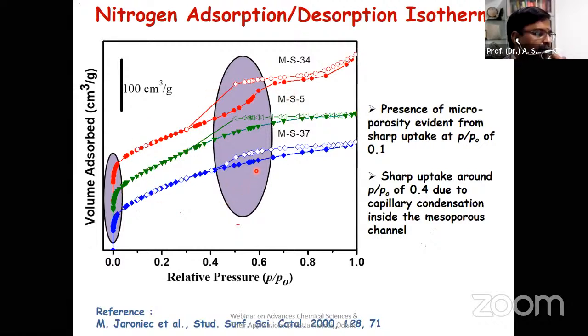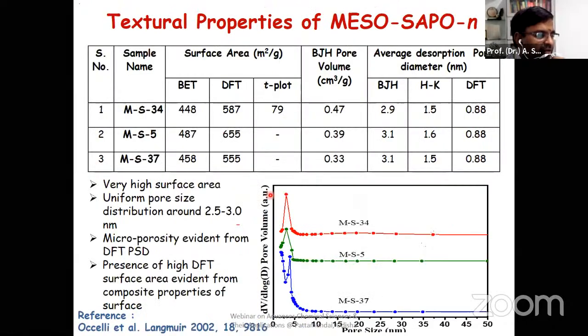How this is going to form, you can see from here. So the material formed has a meso-micro characteristic nature, which we normally confirm with the surface area. You can see the surface area is almost 500, and the pore size is around 3 nanometers. Because micropores are like bricks, they don't show a pore size; they are on the wall, so they don't show any pore. The pore size of about 3 nanometers indicates that our materials are mesoporous in character.